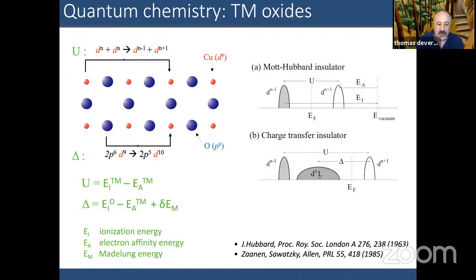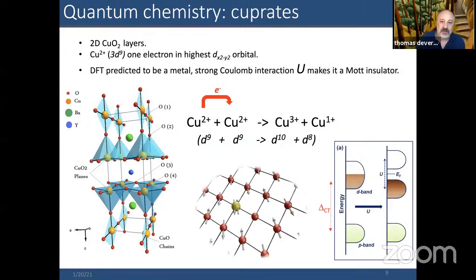If U is greater than delta, then that is panel B here, the charge transfer insulator case, which is where the cuprates lie. But it could be the other way around, where the ligands are so far down that they don't play really a role in the physics near the Fermi level. And so that's a Mott-Hubbard insulator where the gap is controlled by the value of the Coulomb U. So the cuprates, as I mentioned, are well known to be in the second case. But it's interesting, just as